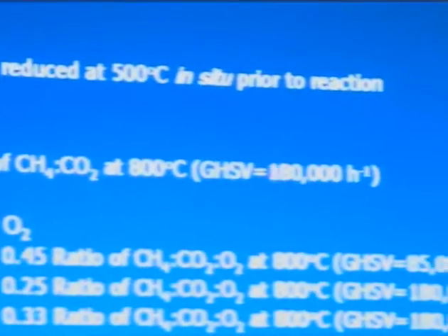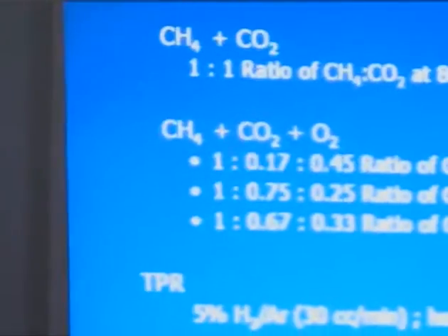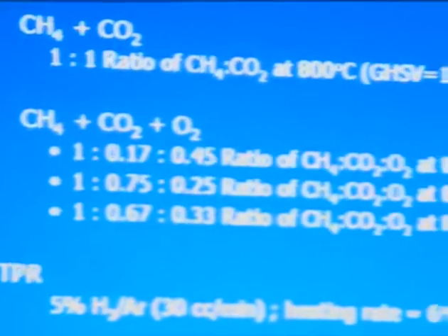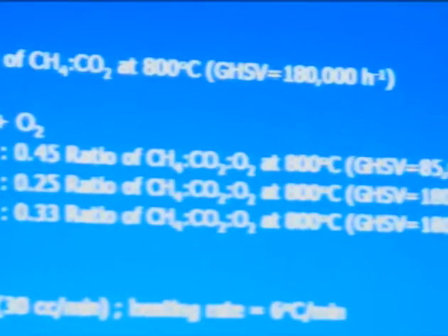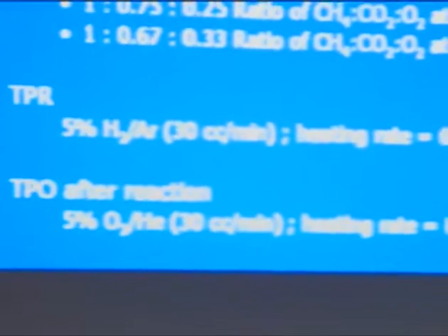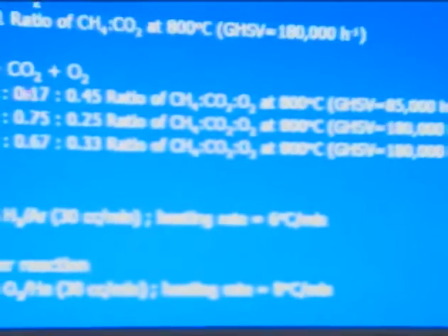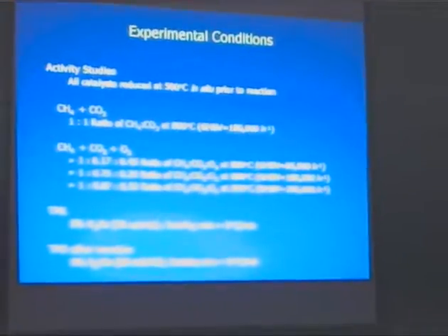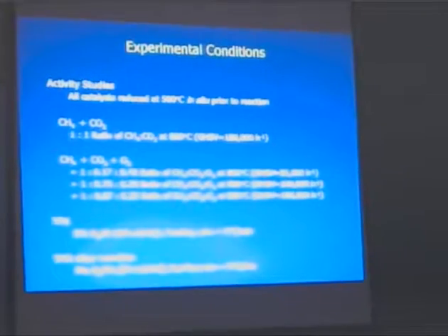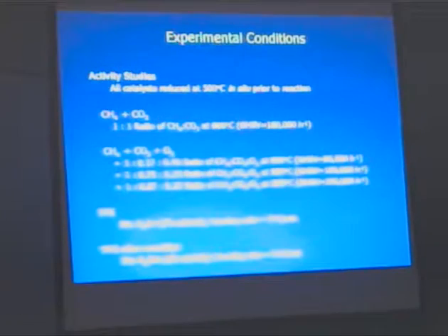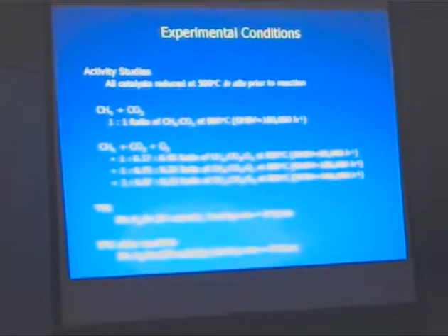When we did methane and CO2, we had a 1-to-1 ratio of methane and CO2 at 800 degrees at high gas space velocities. Previous studies that we had done had all been at the ratio of 2-to-1 methane to CO2 under highly deactivated conditions, and we wanted to do these studies under conditions that would be more reasonable for industrial applications. When we have methane, CO2, and oxygen present, we looked at several different ratios. This first ratio here is along the lines of what you would see for more of a true autothermal reforming condition, in terms of a higher ratio of oxygen to CO2.